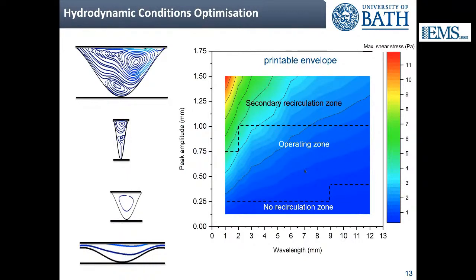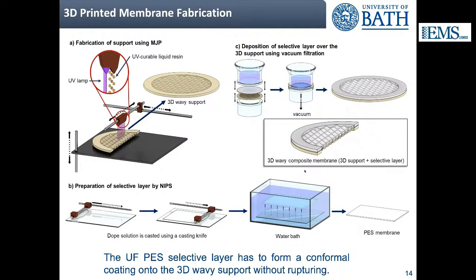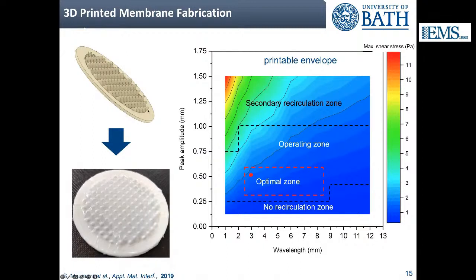The next step to consider is fabricating your membrane. The way we made our membranes is we 3D printed this wavy support, and then we deposited a selective layer, which was made in PES by phase inversion, on top of the 3D printed structure. And what you form is a conformal coating. So the PES selective layer takes the same shape as the wavy support. And so now you have to consider that if your peaks are too high, or if the distance between peaks is too high, you will not be able to get a conformal coating of the PES. And so your actual area where you can get a high quality membrane is this smaller red rectangle. And eventually we try to get the highest possible shear within this area, which is represented by the red dot.